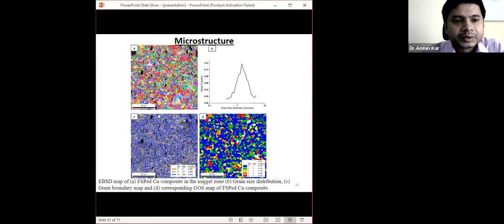Okay. So the microstructure of the base material initially we had taken, how much was it? It was approximately 74 microns. But after the process, the microstructure of the matrix material itself is very, very fine. So according to the Hall-Petch relation, we can expect better mechanical properties, even if we don't consider the reinforcing influence. Depending on the reinforcing particle, the property could be improved further.